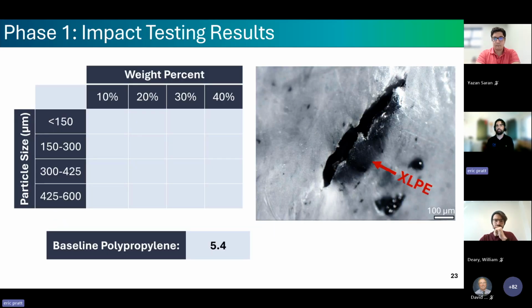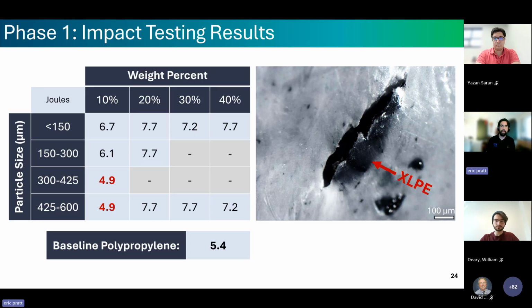Moving to impact testing. Again, this was a critical test for us because of our application. To test impact strength of our matrix, we tested various points along the matrix and then just filled in the middle until the story was told. The same particle size story shows up again in impact testing, but only up to a point. Our baseline, Prysmian's current recycled polypropylene, came in at 5.4 joules impact strength.